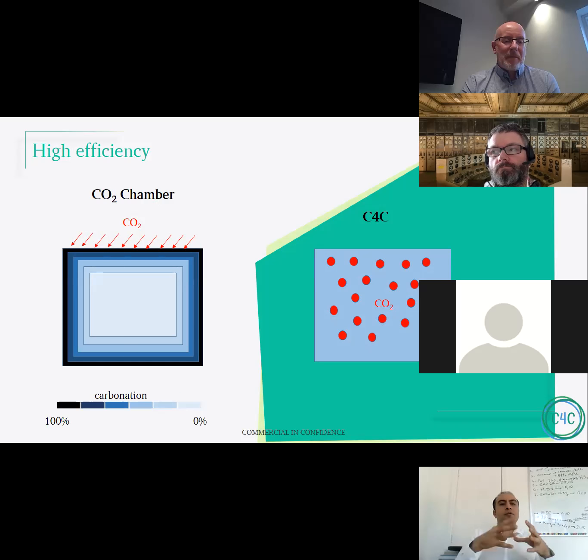The reason behind that is, when we have carbonation, porosity will reduce and it will be really hard for CO2 to penetrate inside. As a result, inside the chamber, we need really high pressure. We have to consume a lot of energy to reach the rate of carbonation we like. And we always have a gradient of carbonation. In our technology, we are mixing CO2 uniformly through our carrier, so we don't have this problem.